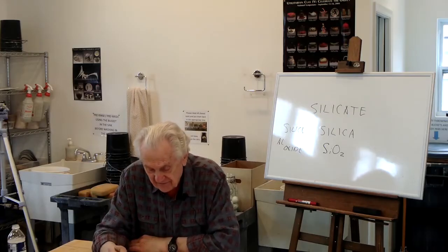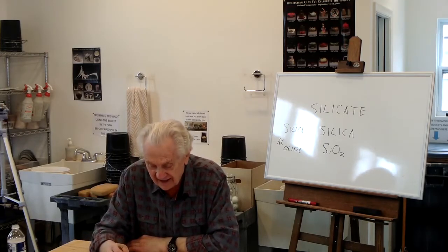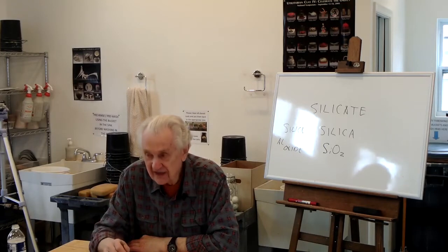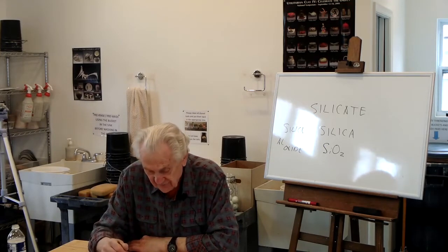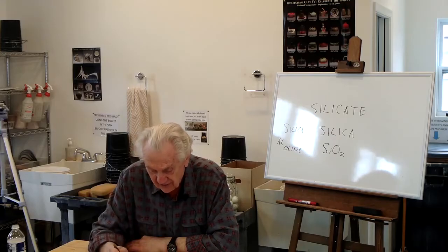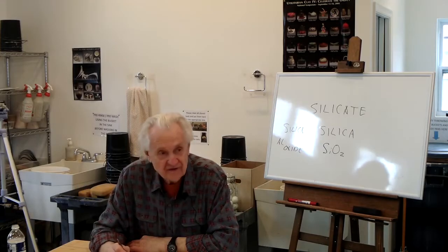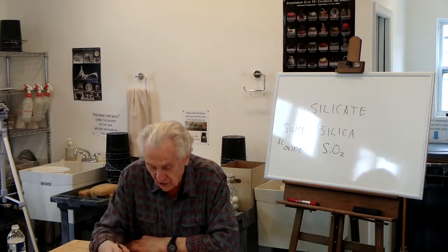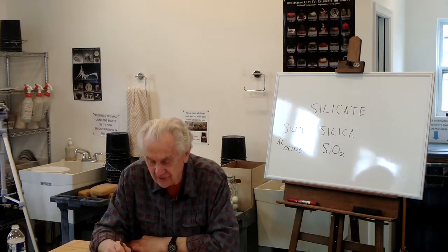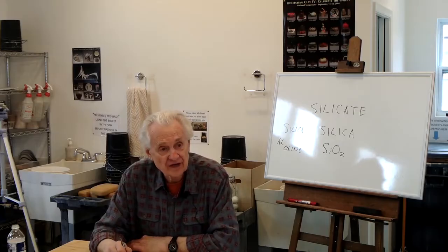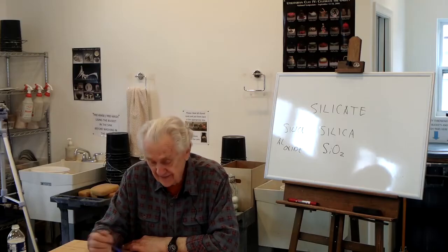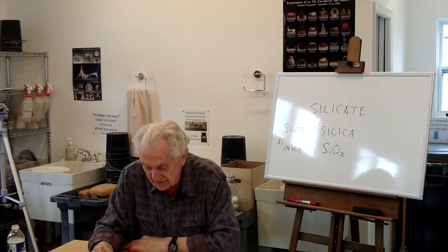And the question you asked, Martha, about what's that at the top, RO, R2O, there is no element whose symbol is R. So the point is, if the formula of an oxide looks like that, RO, something O, or R2O, it's probably a flux. So for instance, if you go down like calcium oxide, in this case, instead of the R, I'm using Ca, the symbol for calcium. So if it looks like RO or CaO, that's probably a flux. Or if it looks like R2O, like potassium oxide, K2O, that's probably a flux. So just looking at the formula, there's a good guess as to what the function of that compound is in the glaze. In the same way with stabilizers, R2O3, well, in this case, it's Al2O3, is the alumina.